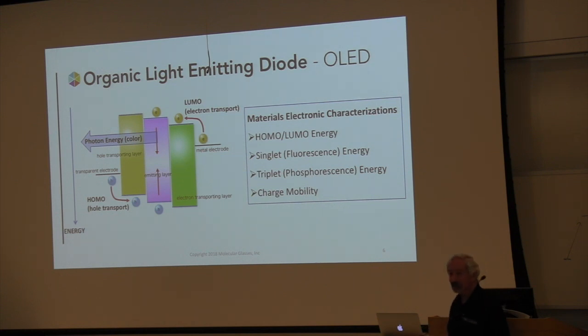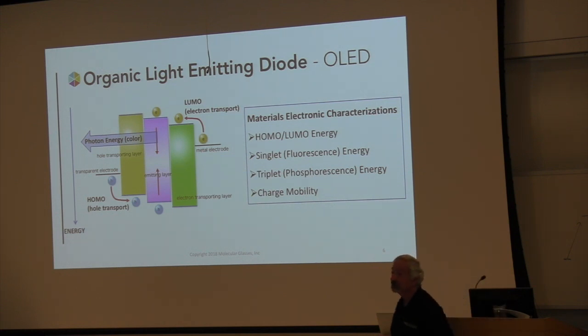Mobility of charges in organic materials is notoriously slow. But these are very thin layers. These are 20, 50 nanometer layers. And so even though the mobility is slow, it's adequate for rapid switching.